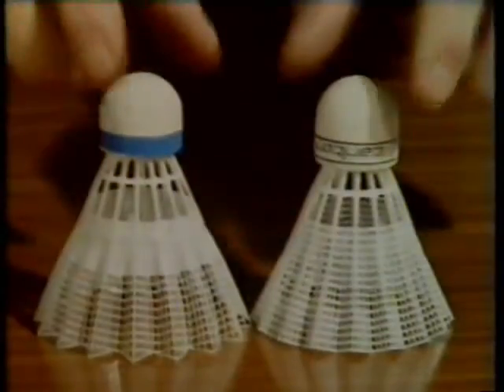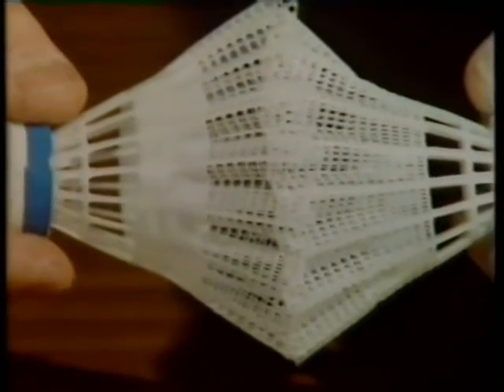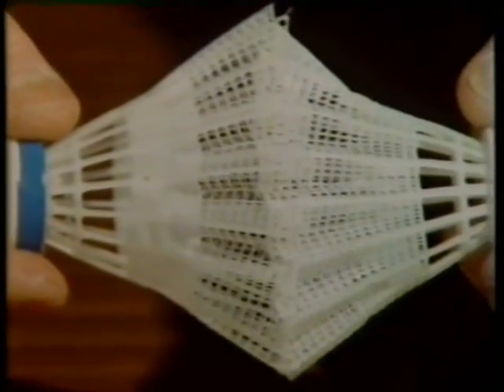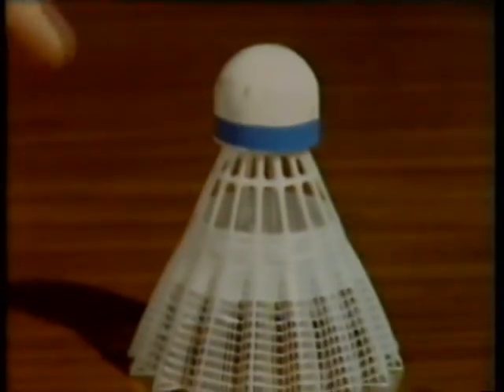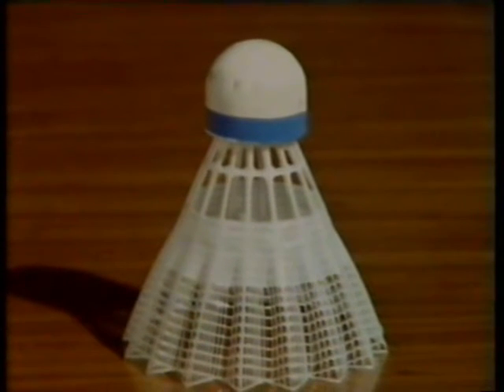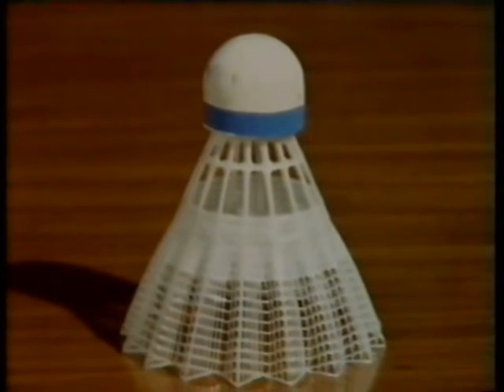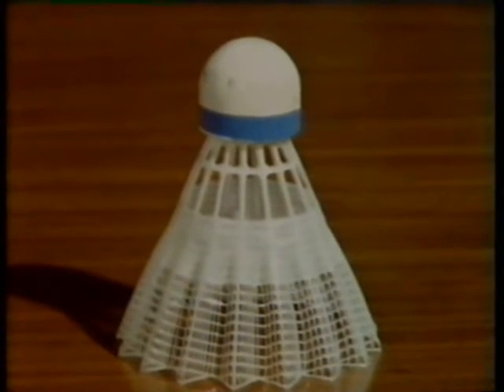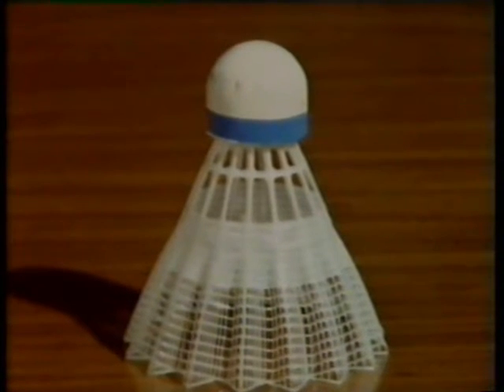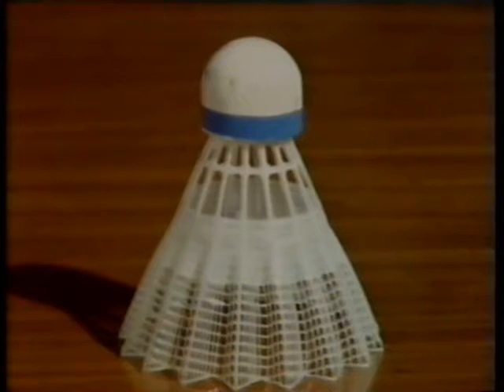Now, increasing the weight was important, as it meant that the new shuttle could now be brought up to the same weight as the feather. But remember, increasing the weight meant it flew too fast. The solution was to increase the angle of the skirt. This technique had been developed to slow down shuttles used in the thin air found at high altitudes. Now it was used to produce a nylon shuttle which has similar flight characteristics to the feather, the weight and so the right feel on the racket of the feather, and a similar sound to the feather. And it's more durable. It'll last much longer in play than the feather.